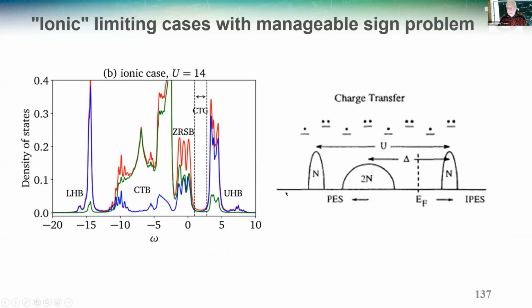And this is the cartoon to the right, and to the left is a real calculation at zero temperature using exact diagonalization. And this model I will call the Ionic Model, and I will explain a little bit later what this Ionic Model is. What you can see here in blue is the copper partial density of states. And you see that copper is mostly in the lower Hubbard band and the upper Hubbard band. Oxygen in green is somewhere in between.